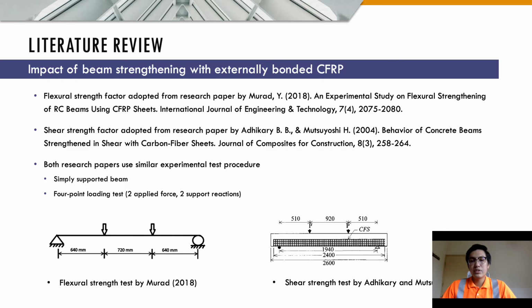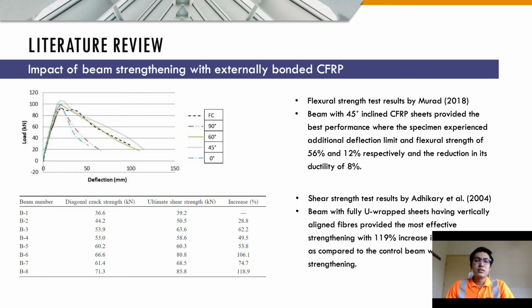Both research papers use a similar approach in the experimental test procedure, which is a simply supported beam and 4-point loading test. So the picture on the left is the test procedure illustration of flexural strength test by Murad, and on the right is the shear strength test by Adhikary and Mutsuyoshi. The above figure is the test results of flexural strength and the below figure is the test results of shear